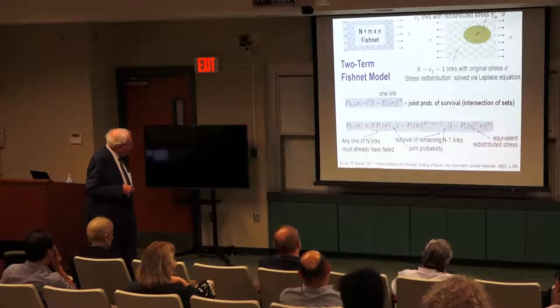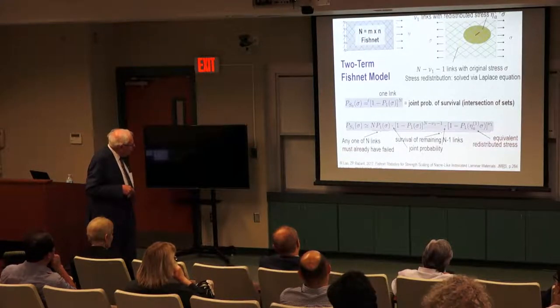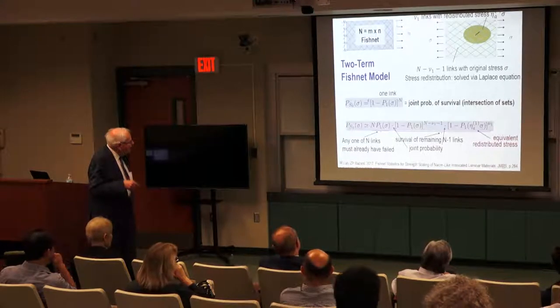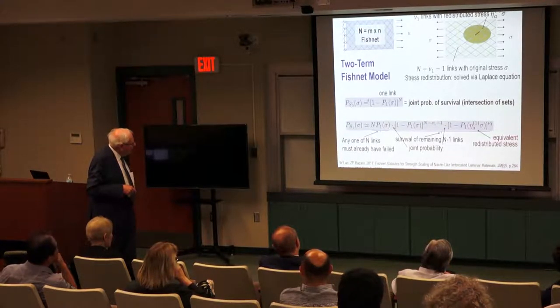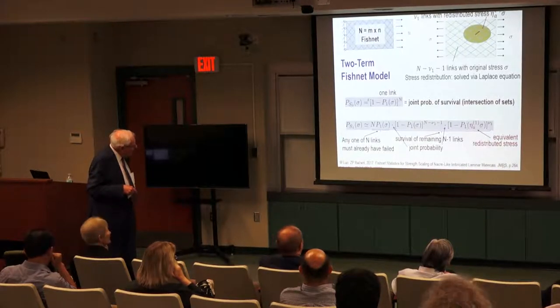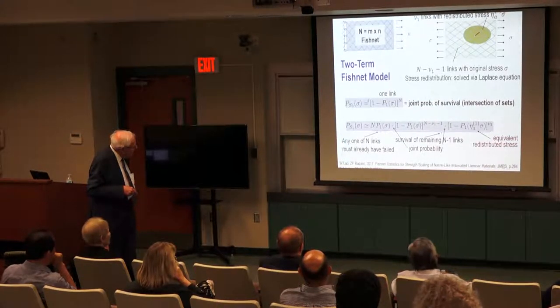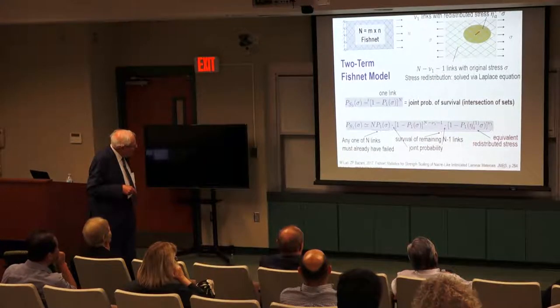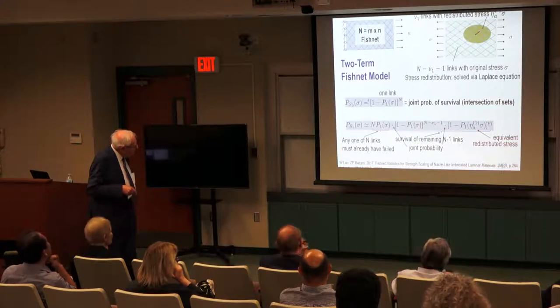Now, for the second term, we can argue similarly. It can start at any of n points. There are n elements here in the fishnet, and that must happen simultaneously with survival of the rest. So we have survival probability is this difference, one minus failure probability, and it must occur jointly. So n, but you must distinguish elements which are redistributed, which are not.